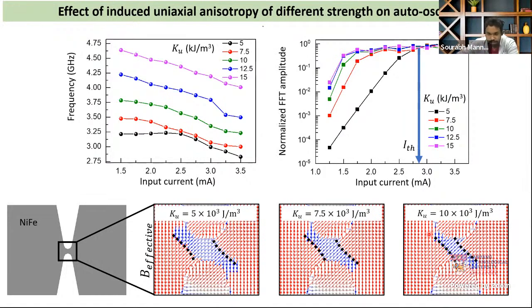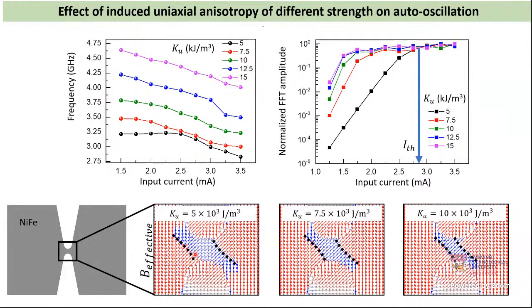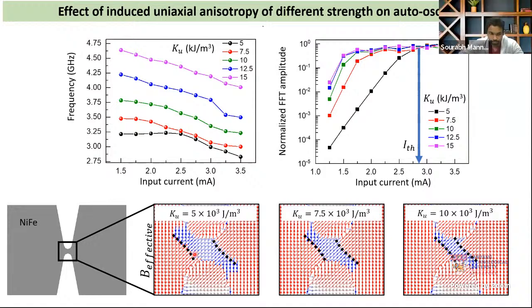That is the point I discussed actually, because as you see, with the increasing Ku, this confinement region is shrinking. So once the oscillation starts, it also starts spreading out from the constriction region. And that's why we actually see the opposite behavior here, because we get higher amplitude of the oscillation. The spin waves generated here are no longer confined in this region, and they start spreading out around the constriction. So we get a much bigger oscillation volume, whereas for smaller anisotropy, the oscillation is confined in this region only. So this is actually the nanoconstriction geometry effect and the anisotropy, of course.